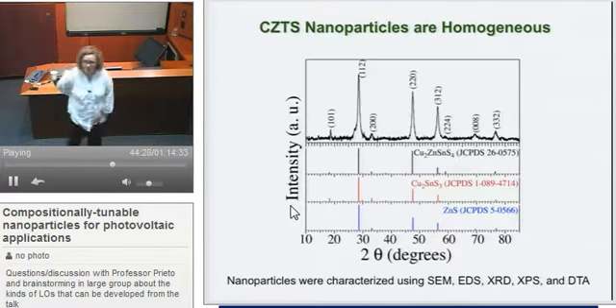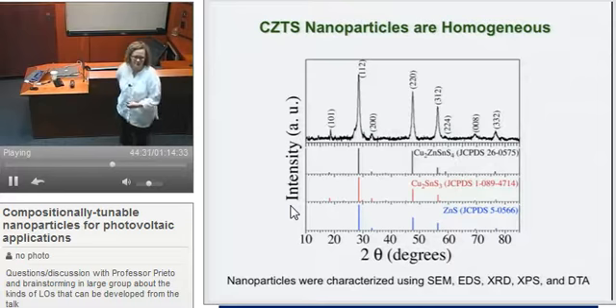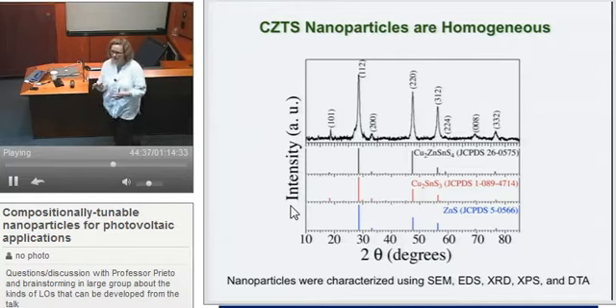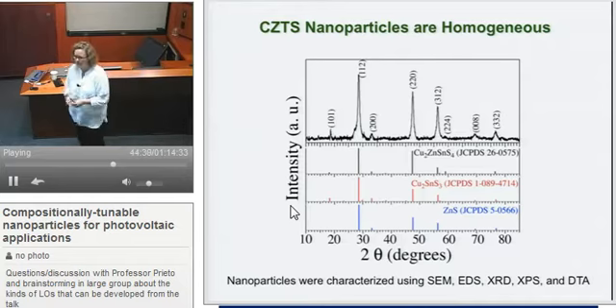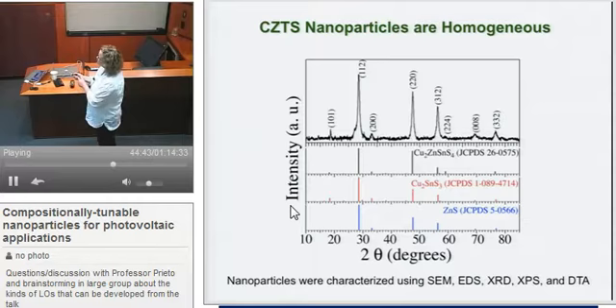Now, X-ray diffraction. We take X-ray diffraction patterns like organic chemists take NMRs. That is the first thing we do. And in this field, or for this particular compound, it is, although not exactly useless, pretty close. So the powder pattern at the top shows the peak broadening, which we use to calculate particle size. You can see it's all indexed to CZTS. We generate the reference pattern from a single crystal structure. But look at what's important.